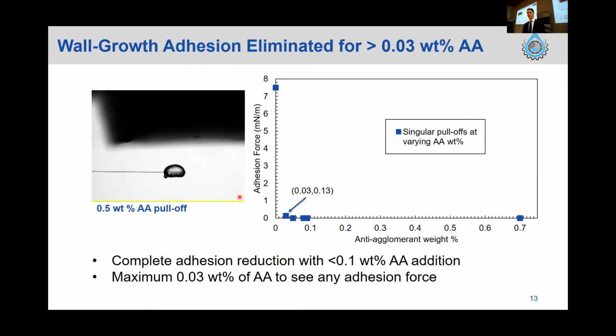And the findings from that was basically trying to find a minimum weight percent where an adhesion force could actually be measured. And that was all the way down at 0.03 weight percent anti-agglomerant in the system, which produced an adhesion force of 0.13 millinewtons per meter, which is quite comparable to what was seen for the baseline and the time variant, which is relatively low compared to the wall growth with no AA present. And basically the summary from that is that quite confidently there is a complete reduction in that adhesion force below 0.1 weight percent anti-agglomerant.